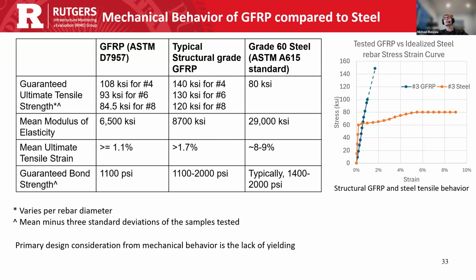So a lot of the considerations with the early rebar have been addressed with better designed ribbing, etc. And of course the ultimate tensile strength has increased a decent bit. And you can see that compared to steel, it excels in tensile strength, but the modulus is much lower, so it's a less stiff material. And maybe most critically, it strains a lot less. And you can see that in the graph on screen. You can see the linear behavior of GFRP up till failure, much lower ultimate strain, but steel has the characteristic ductility that we know and we design around that's very familiar, where there's this very drawn out ductile failure.